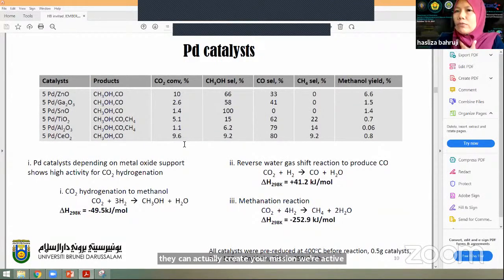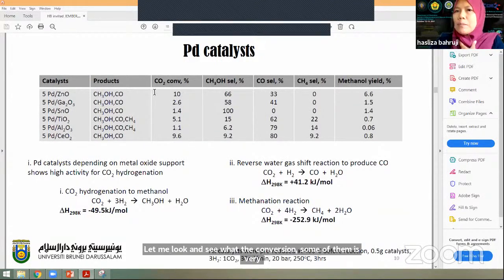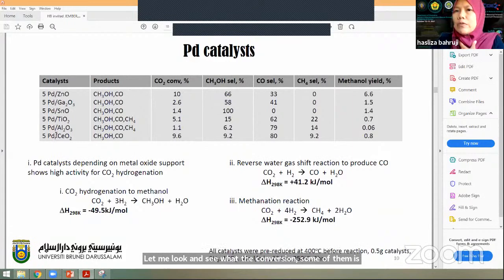When we look at CO2 conversion, some of them are very active, for example palladium on zinc oxide, and some are not really good, for example tin oxide and alumina, but when we have ceria, we also have a high conversion. The difference between these supports is the selectivity toward methanol. The only catalyst that has both high selectivity and high conversion to methanol is the palladium zinc oxide catalyst.